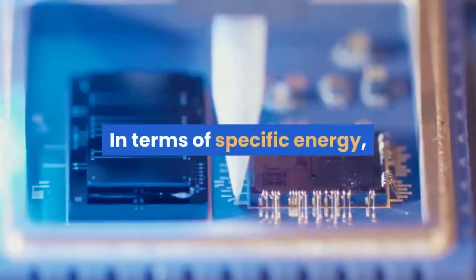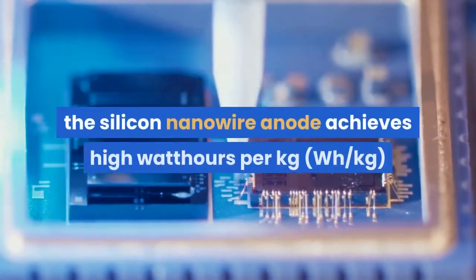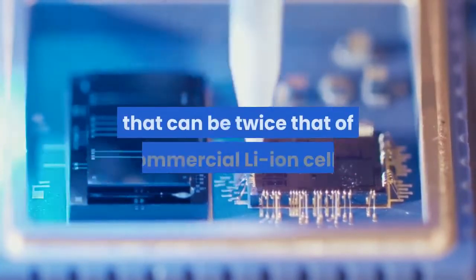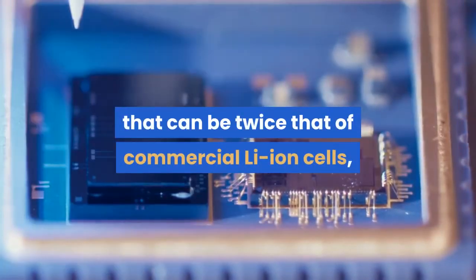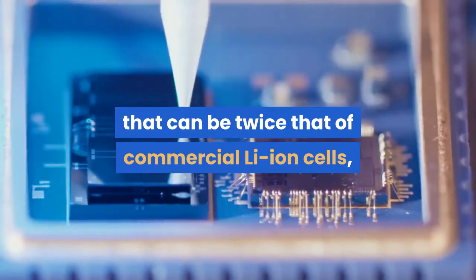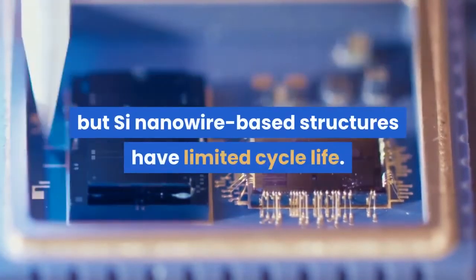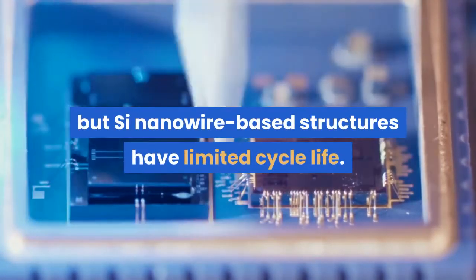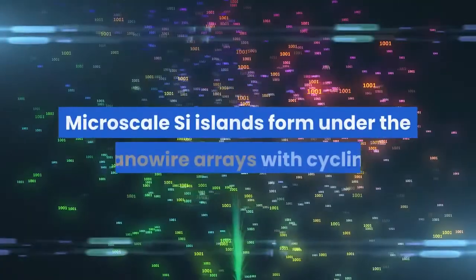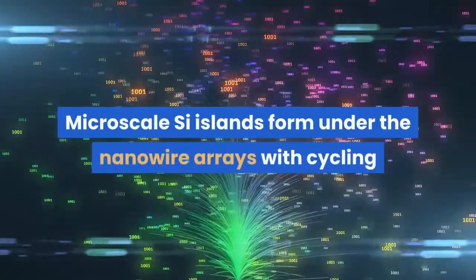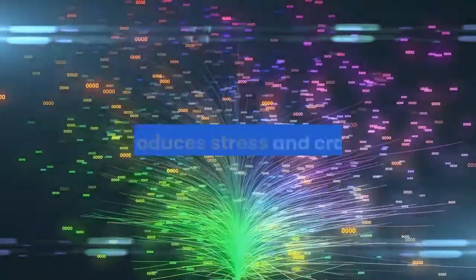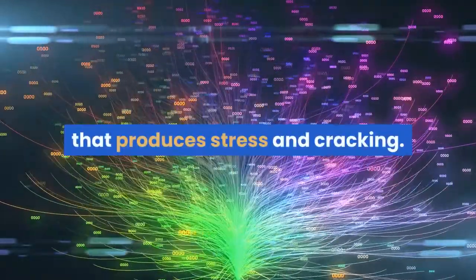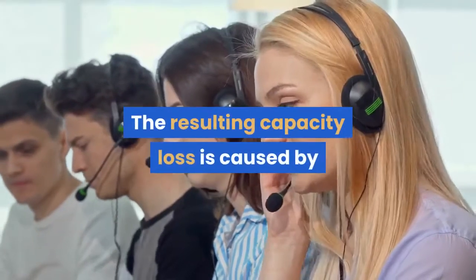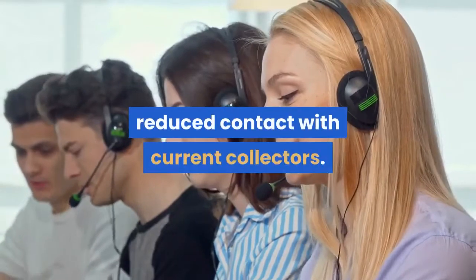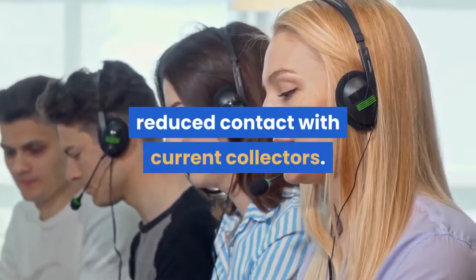In terms of specific energy, the silicon nanowire anode achieves high watt-hours per kilogram that can be twice that of commercial Li-ion cells, but nanowire-based structures have limited cycle life. Microscale Si islands form under the nanowire arrays with cycling that produces stress and cracking. The resulting capacity loss is caused by reduced contact with current collectors.